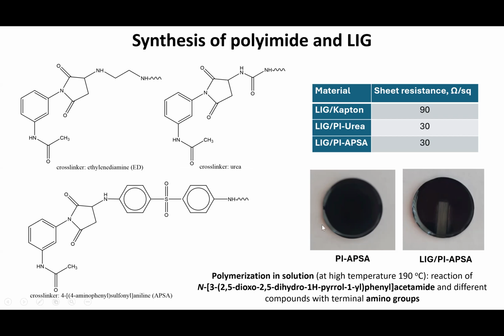It's a bit hard to see visually because these are very dark polymers. You see the images here, and you can see a rectangle of graphene on this sample here. But it's more difficult to see than on the white polymers that I've shown you before. However, we noticed that the sheet resistance is quite low for this. It's better than we can get on Kapton, 3 times better in some cases, which is good for electronics applications.